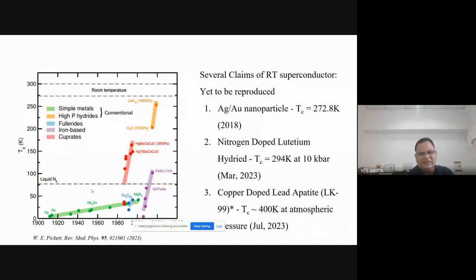Magnesium and boron both are lighter elements. So it was known that if you do calculations based on TC, theta D, N of EF, and interacting potential, you can reach in a strong BCS limit to 40 Kelvin. High TC cuprates were yet outside, and till date they are outside. Then the next revolution happened around 2006 by the Japanese scientist Hosono's group, that iron arsenide, the pnictides, the iron-based superconductors, came in the picture, and their TC was above 40 Kelvin, in fact up to 50 Kelvin.